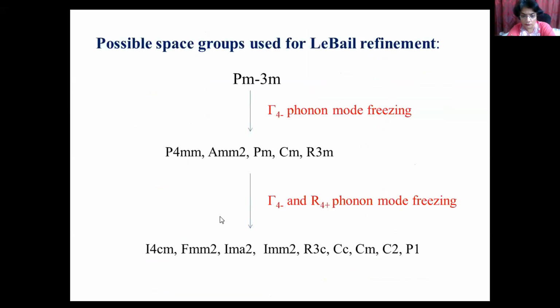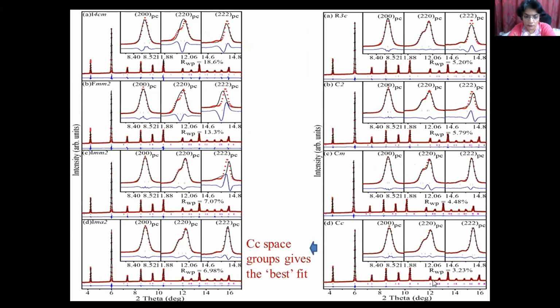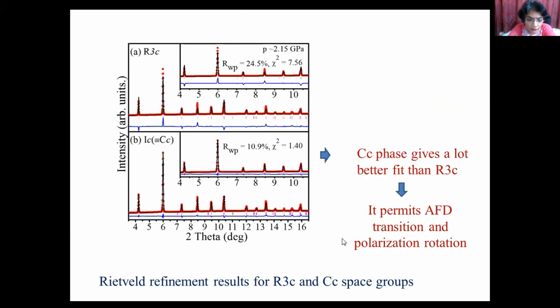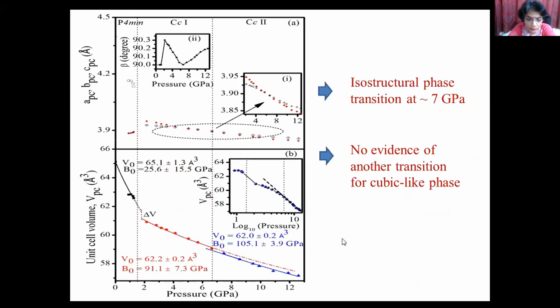Now, to again confirm this by refinement, we incorporated the possible space groups which can be observed because of zone center and zone boundary optical phonon modes. These were the possibilities. Except triclinic, we tried all these space groups and we found that the monoclinic Cc group gives the best fit, which involves the polarization rotation as well as the AFD transition. It kind of combines all the pictures.